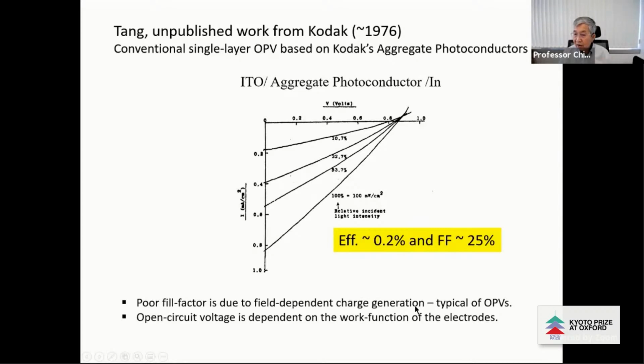Unless you reach a high field, the charge generation efficiency is poor, and so the fill factor is poor. It's typical of organic solar cells in those days. And the open circuit voltage at this point right here is strictly dependent on the difference in the work function of the two electrodes sandwiching the layer. So that was the beginning. I spent maybe a year struggling with this, but this is probably the best I could get with single-layer devices.